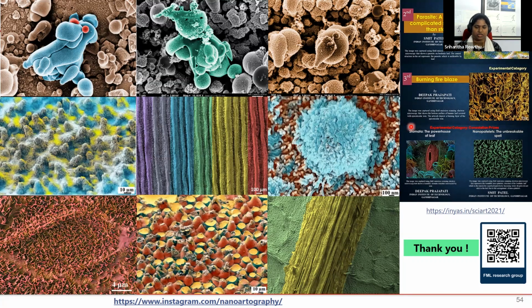We don't want that. So we are essentially trying to say that I'm going to give each of these particles some charge so that they will be in stable equilibrium. Okay. So now for the mechanical breaking, what did we do? One is the probe sonication. Simply, it's like a probe. It will essentially give some energy and break down the particles.